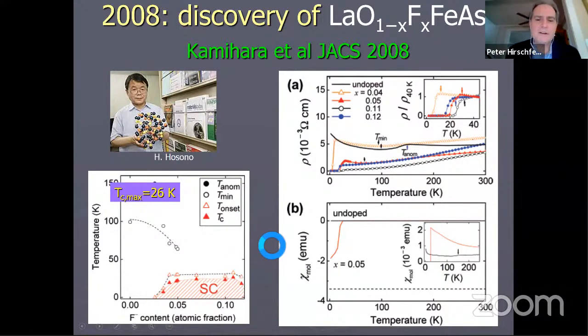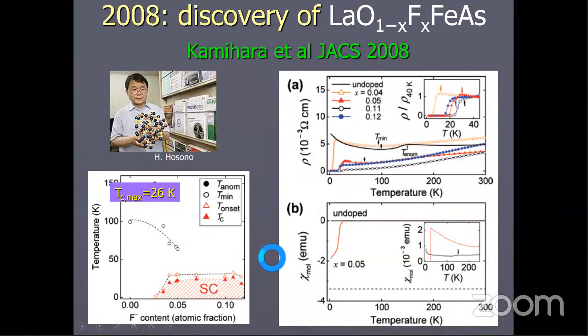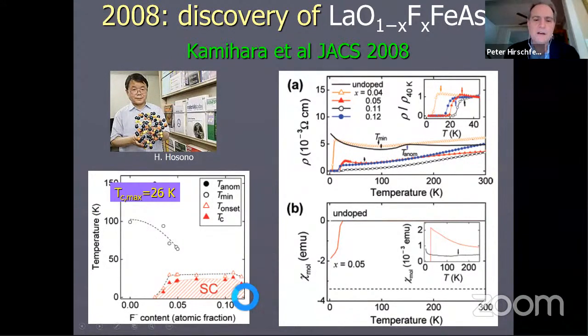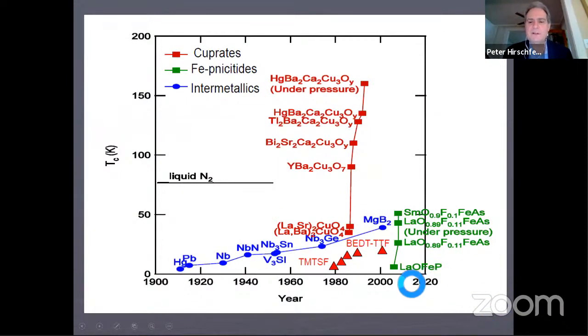Yeah, I'm sorry. So I'm just showing you the data from the first paper here. First of all, the existence of a superconducting dome, rather similar to the cuprates. That's one of the things that got people excited. And there was an anomaly in the transport at higher temperatures, which turns out to be a magnetism, long-range magnetism. As in every good experimental paper about superconductivity, the magnetic properties were also explored. And so this was quickly discovered to be a new class of materials based on iron, which was again surprising because iron is supposed to have a moment and that's supposed to be bad for ordinary S-wave superconductivity.